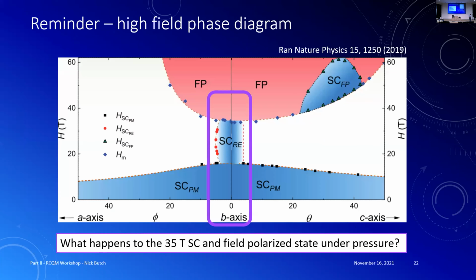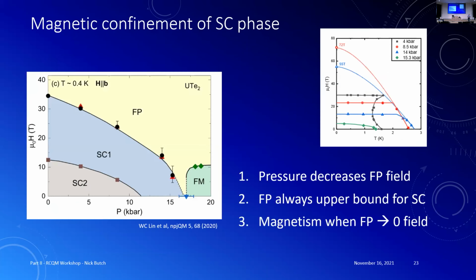So I just recall again, 35, right? So you apply pressure with the field along this direction. I'm really not doing it justice. This is not an easy measurement. You have to do a pressure cell, and this is done in Tallahassee, but this is what the phase diagram says, okay? So as you apply pressure, this field polarizes metamagnetic transition gets pushed down to zero above a critical pressure somewhere in the 1.5 GPa range. Superconductivity is encapsulated by it, so it can't go past. This says FM, be a little bit more agnostic. There's some kind of long range order on the other side. Okay. And these are sort of the conclusions here.